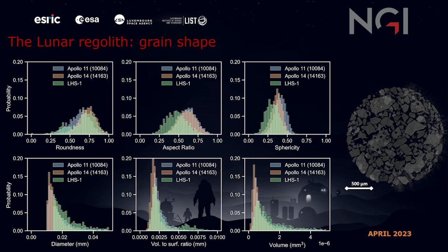So first, in the bottom left, you have the diameter of the grains, so like an equivalent diameter. And we see that the distributions of these line up quite well, which makes sense because the simulants are made to follow the particle size distributions of the lunar regolith. However, if we look, for example, in the top middle at the aspect ratio, we see that there's a shift between the distributions of the Apollo 11 and 14 samples and the LHS-1.